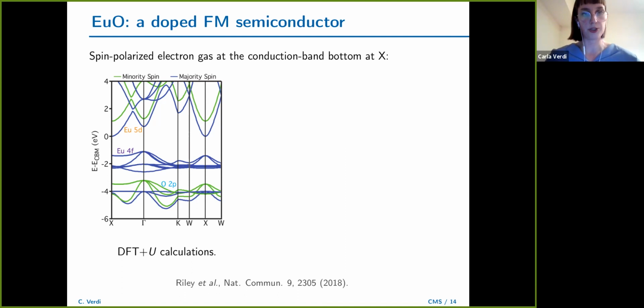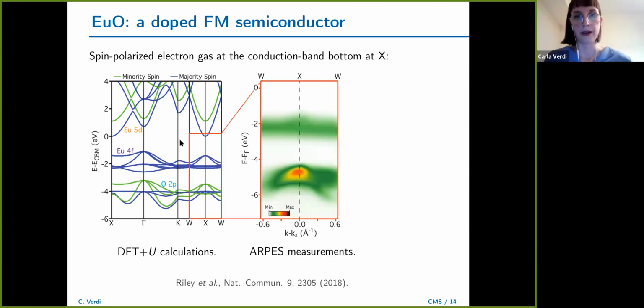So first of all, let me just show you the band structure of europium oxide. So it's a ferromagnetic semiconductor, which can also be doped. Basically you would have some electrons here at the bottom of the conduction band at the X point. This is our DFT band structure. And this is, for example, the ARPES intensity map for this region here.